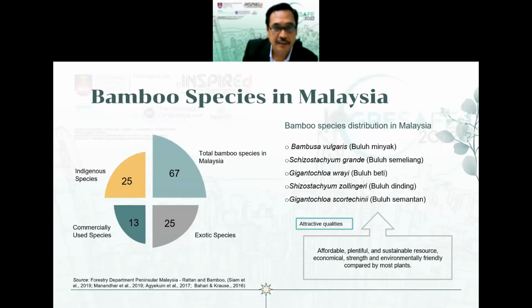Okay, so for the bamboo species that are suitable for construction, I did a research myself on the buluh semantan, for the bamboo fiber itself. I found that it possesses the highest strength for compression and tensile strength. So it shows that buluh semantan is one of the best bamboo species that can be used in constructions.